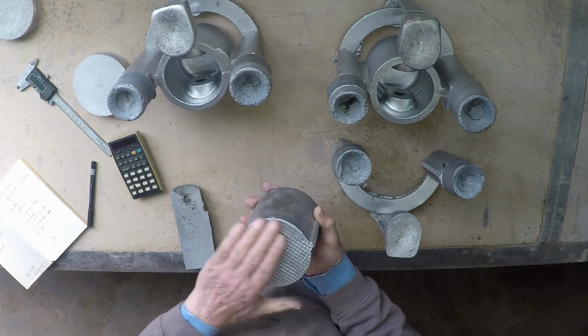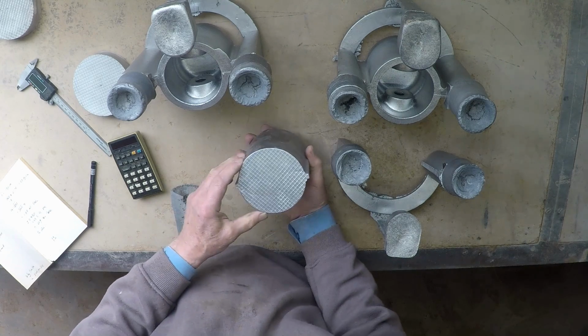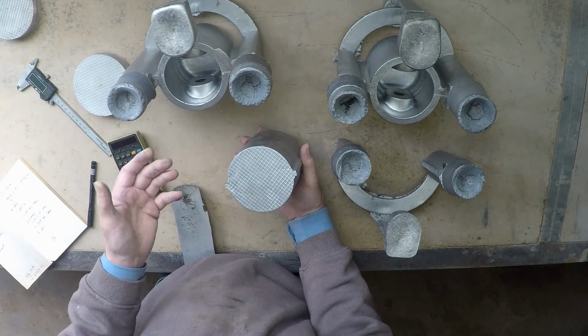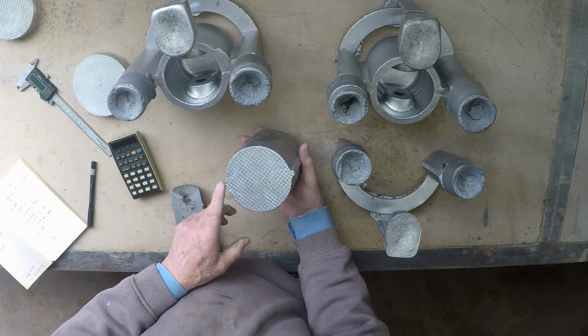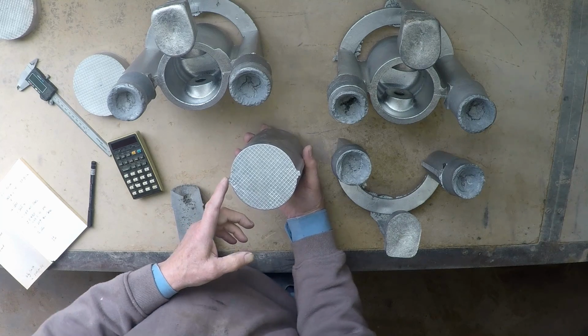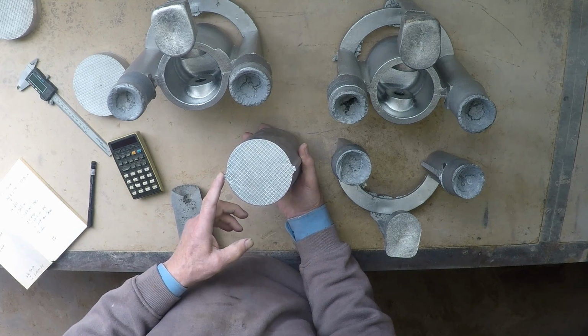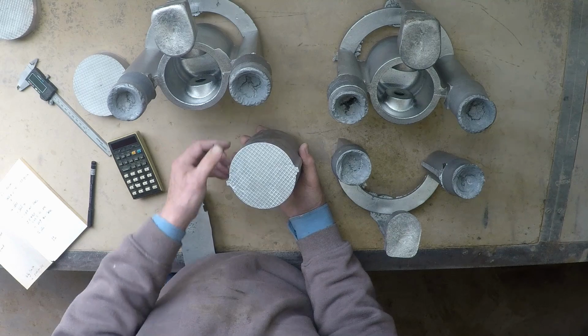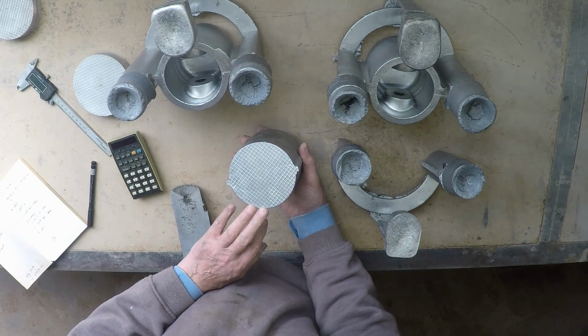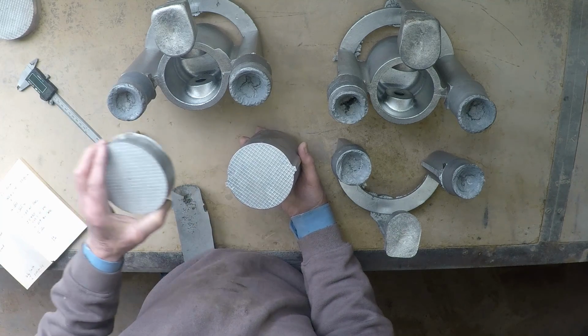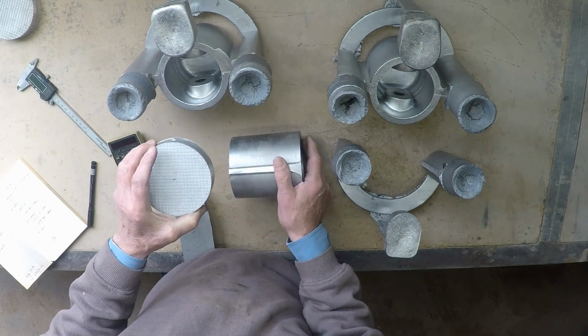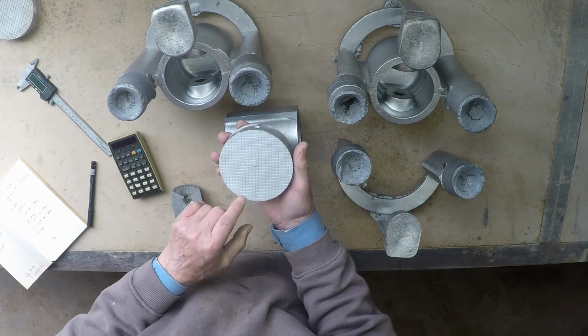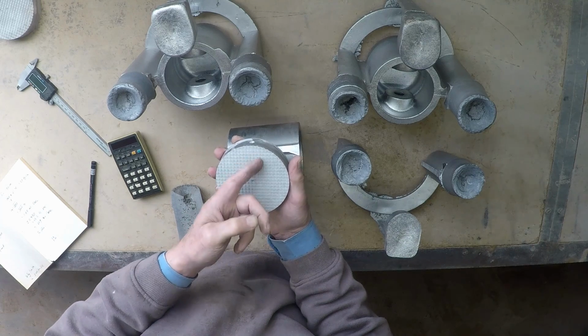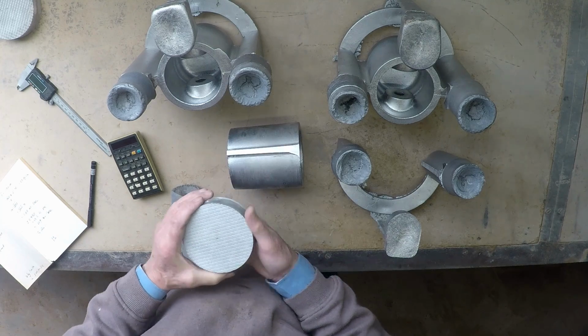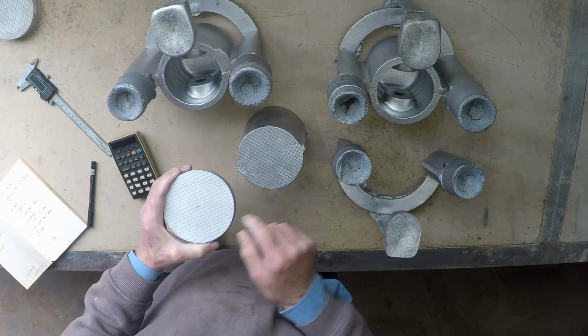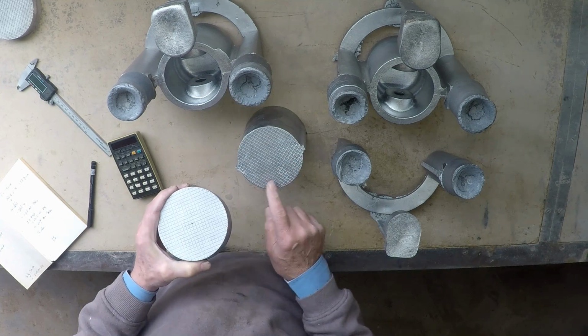We have in particular chilled the bottom, and normally when you cast metal against a chill, it tends to come out a bit ordinary. You get sort of flow lines in it, and the flow lines can even trap a bit of air or gas, and you sometimes have to take quite a bit off the casting to get that to clean up. But I'd noticed that Japanese castings, automotive castings, cylinder heads, that sort of stuff, engine blocks, often have this cross-hatched pattern on them, which I wondered what it was for, and I thought, well, I'll try it on the little chills we used, and it's brilliant.